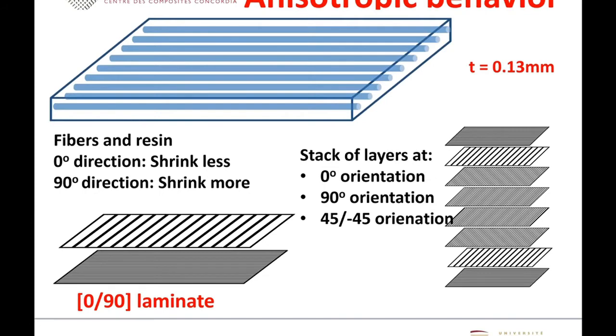So, saying a little bit about the anisotropic behavior. Anisotropic behavior means the properties depend on the direction. For example, you take a look at one single layer of the composite, such as the case of carbon epoxy here. Then you can see the blue lines, which represent the fibers. These fibers are fairly small. Normally the diameter of a fiber is about 10 micron. The diameter of a hair that we have is about 100 micron. So the diameter of this fiber is about 1/10 that of a hair.